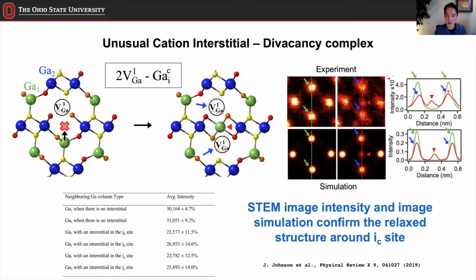So what that means is, as I said earlier, the image intensity depends on the number of atoms, right? Because this is high angle scattering. So the fact that the gallium column intensity is lower means that this column is actually missing atoms. Missing atom means vacancy, right? So that way we can confirm that this column actually contains vacancies. Whenever we have this extra intensity from the interstitial column, then we have vacancies. So they are almost always paired. And that way we were able to confirm that whenever we see the interstitial, it's actually showing us the interstitial-divacancy complex.